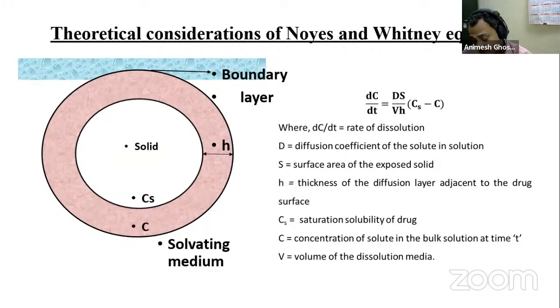So the concentration of the drug at the saturation layer or boundary layer is basically constant, because it acts as a reservoir. If some of the drug goes to the bulk, there will be a vacuum, so from the matrix the drug will come to this layer. That is one type of apparent zero order rate kinetics. The concentration of the drug at the saturation layer or stagnant layer is constant. That is nothing but the saturated solubility of the drug. So from this equation, we all know this equation, dC/dt equals DS/Vh times (Cs minus C), where we have the surface area, diffusivity, stagnant layer thickness, and the concentration.